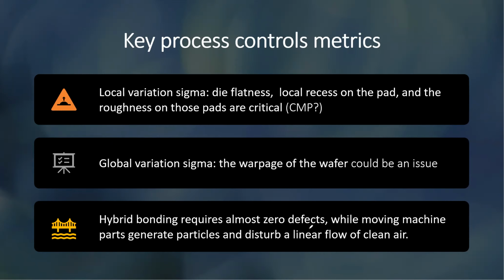You cannot remove the particle completely, of course, but suppose your copper pillar is 10 micron, and you have a particle of 100 nanometer, 10 nanometer, it doesn't really matter, right? Because your copper pad is 10 micron. But if you scale it down, say I want the copper to be 200 nanometer, then if you have a particle that's 100 nanometer in size, that impact will be different. The yield number is not going to look good.